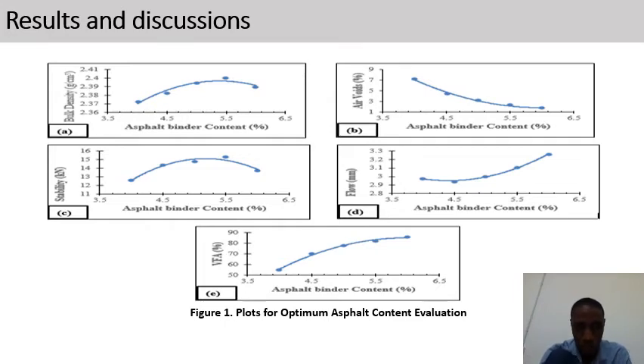This figure, results and discussion, is showing the plots for the optimal asphalt content evaluation. As you can see, plots A to E show how bitumen content affects the bulk density, air void, stability, flow, and the VFA. These five plots were used to obtain the optimal asphalt content: first at maximum density, at 4% air void, at maximum stability, at 3 mm flow, and then at 75% VFA.